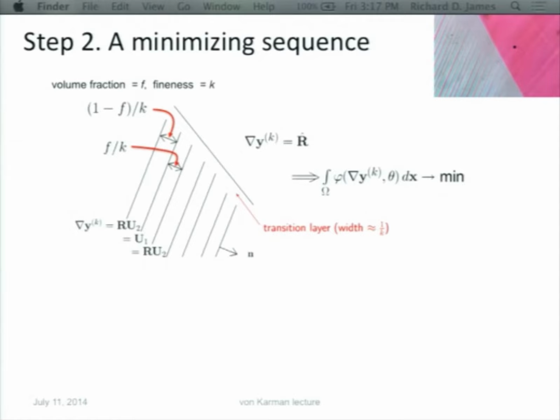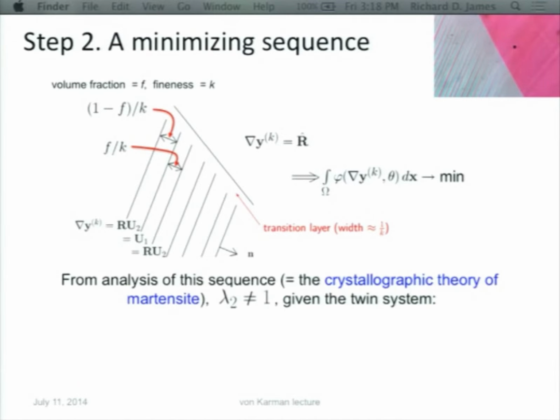So I try the next best thing. I interpolate with a transition layer of width 1 over K. So I simply interpolate two deformations. And I find that, in fact, you can drive the energy in that transition layer to 0 by making K larger and larger, as long as certain conditions are satisfied. So what has to happen is the normal to this interface is to be just right, and the volume fraction F has to be just right. And you work that out.